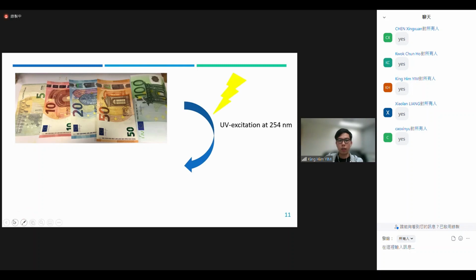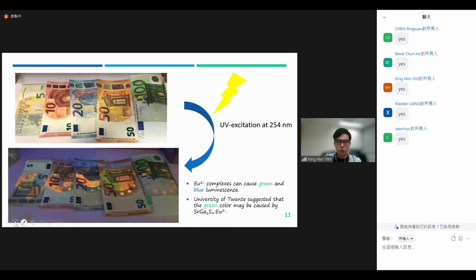So if you excite the banknote at 254 nanometers, you will observe a blue-green emission on the banknote. And this emission is actually attributed to the presence of Eu2+. This time, people use a Eu2+ complex on the banknote for security ink. And the actual structure we don't know because of security reasons. But one university suggests that the green color may be caused by this Eu2+ complex.